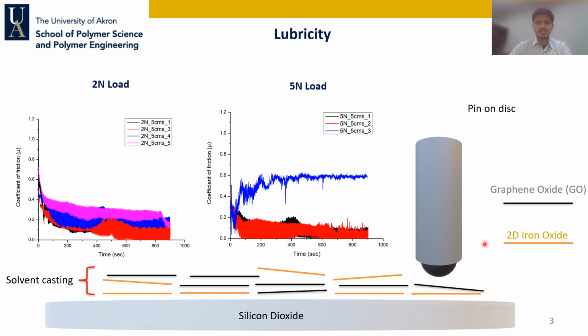And just the pure 2D iron oxide was not feasible for the lubrication study, and it showed coefficient of friction values much higher, close to 0.6.